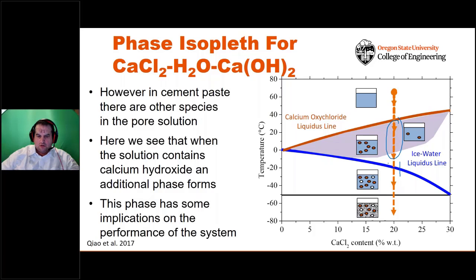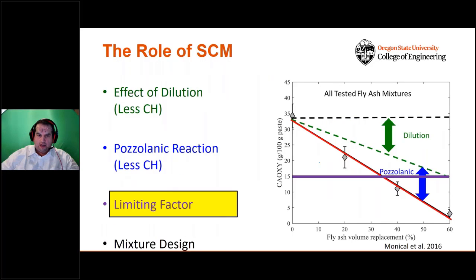There's a couple things that are really scary about this. One, it's about a 300% volume change. The second thing that's really scary about this is the temperature range that it's happening in. So while we may have 150 or 200 freeze-thaw cycles a year on a concrete pavement, we may have 800 oxychloride cycles because of the temperature range that it's happening in. So this can have some really significant impacts.